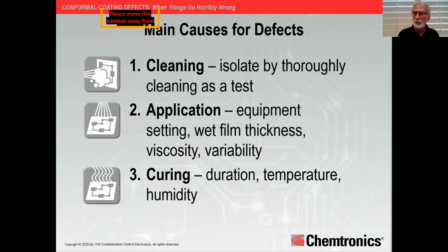And then, of course, you have the curing process, the time, temperature, in some cases, the humidity conditions in which you're curing that coating. If you're not doing it properly, if you're not following the coating manufacturer's recommended guidelines, that could set you up for a coating failure or a defect.